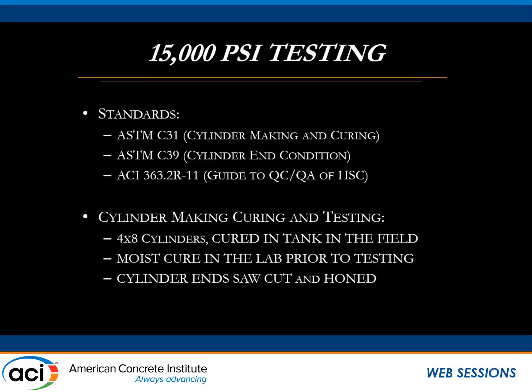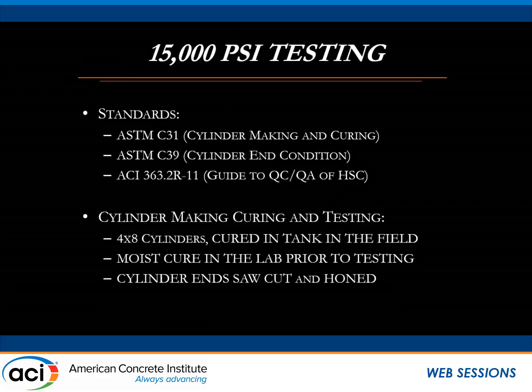One of the biggest things we found out on this job about the 15,000 is that you can spec out 15,000, but a very important thing is the curing and the testing of the cylinders. When you go above the 12,000 threshold, there's little education within the industry on how to do it, unless maybe you go to Walter Flood IV. And some of the testing labs, not a lot of them, treat these cylinders like a 6,000 or 8,000 mix. So the standards of the code are not very stringent. There's some flexibility. The latest guide is ACI 363, which gives some flexibility for QA, QC.